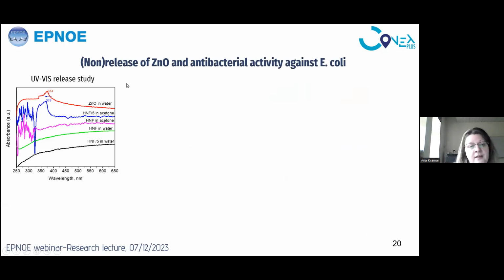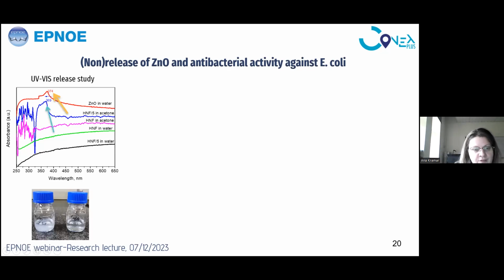We also studied the potential release of zinc oxide when we put these nanofibers in water. We expected that once we put them in water, once we dissolve polyethylene oxide, zinc oxide will also be released. But this wasn't the case. As you can see here, this black line is actually 5 days. We kept our material in water for 5 days, and we don't have any peak that corresponds to zinc oxide. But when we added acetone and, in fact, dissolved our material, we found the peak of zinc oxide. Here you can see it on the image as well, after the addition of acetone. When we have zinc oxide, we have a release. And in this case, when we don't have zinc oxide, the solution upon the addition of acetone is transparent.